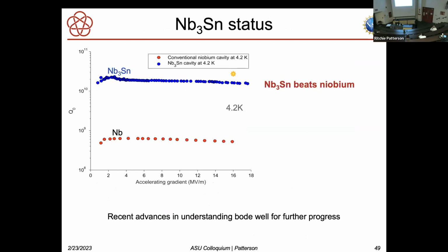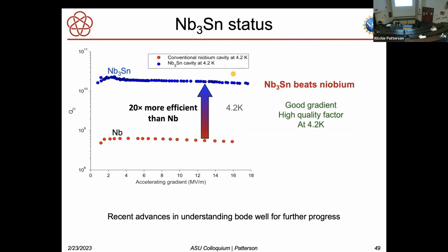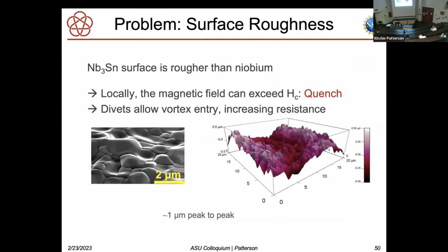And the result of that is that here's now the quality factor versus the accelerating gradient. For niobium and for niobium-3 tin, this is at 4.2 Kelvin, and niobium-3 tin beats niobium by a very large factor. It's 20 times more efficient than niobium. So all of this bodes well, but there are problems still.